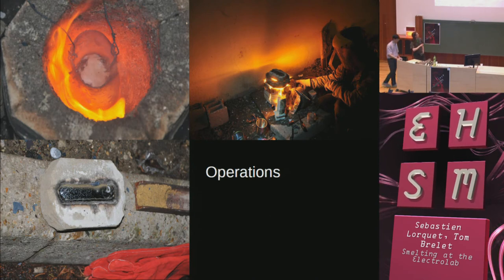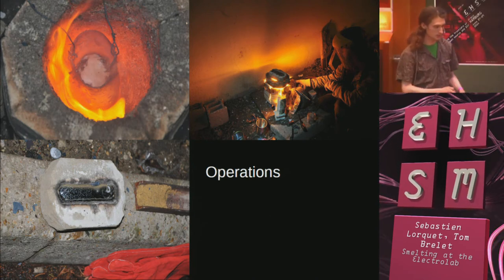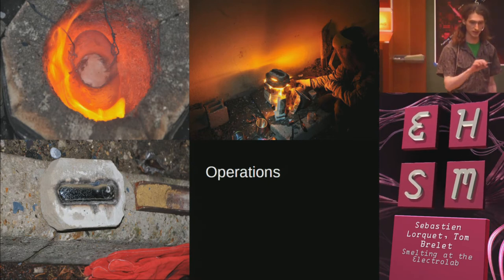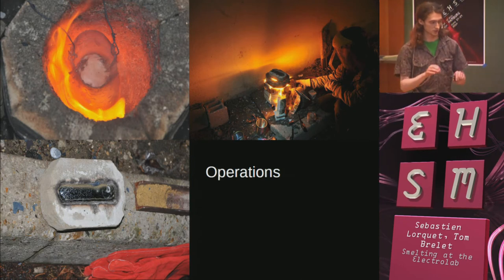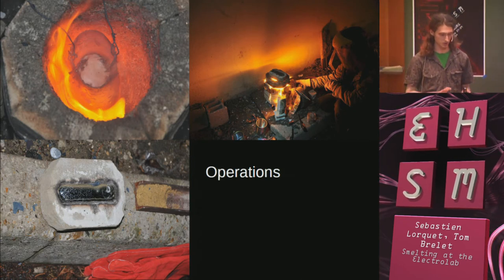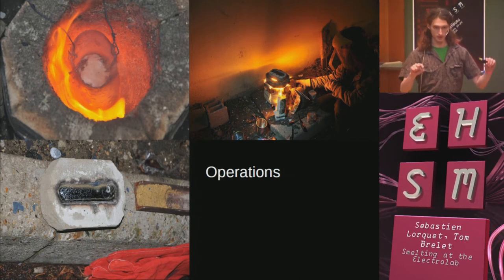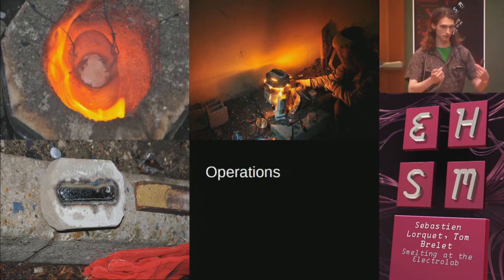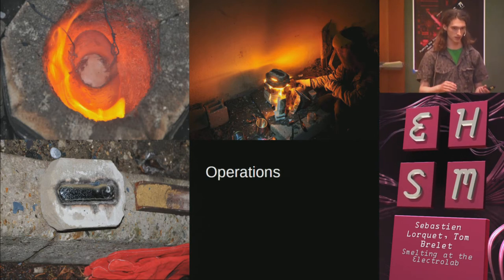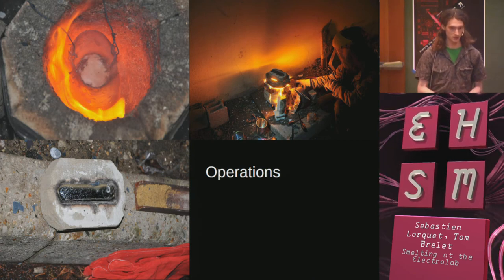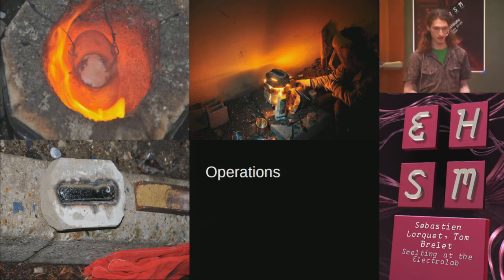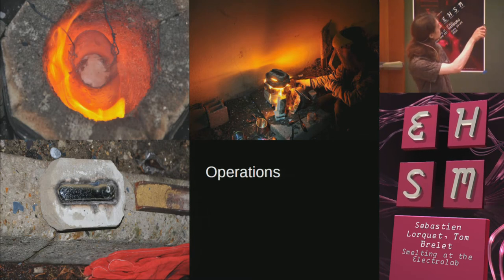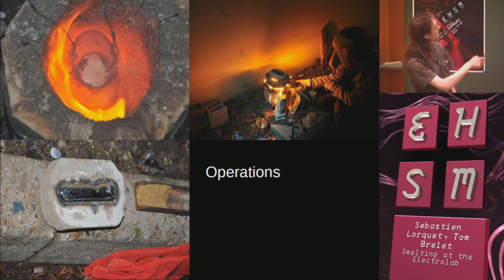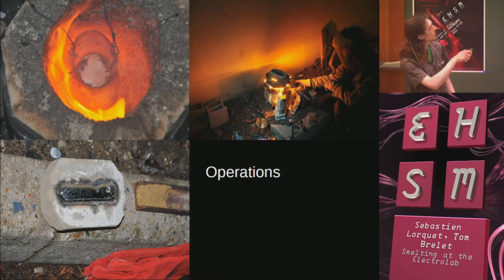So this is really important because there is a lot of oxide on the surface of liquid aluminium, and the salt melts at approximately 500 degrees. It covers the top of the metal. It dissolves the oxides, and it prevents oxidizing by ambient air. So it improves the quality of the metal. You can see here, the metal is very brilliant or polished. I don't know the right term.